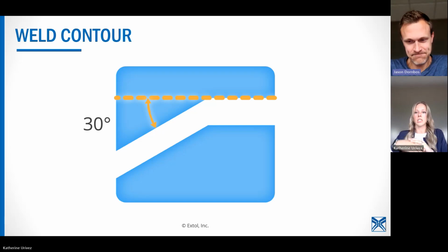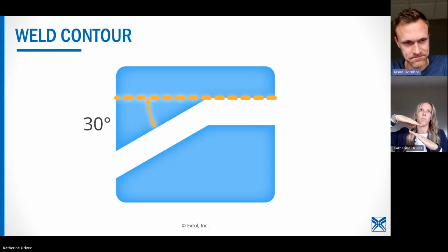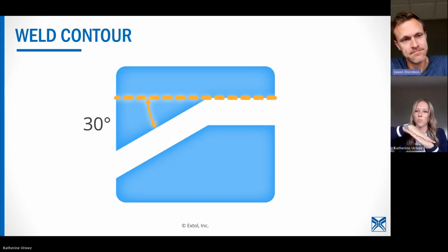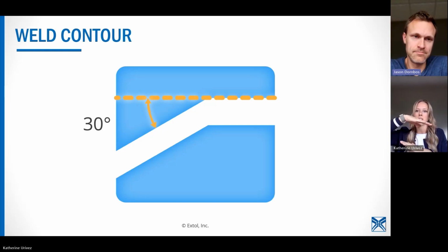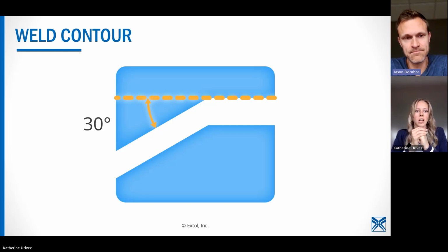The reason for this is when the parts come to seal together, that angle starts to act as kind of a slide. And so you're smudging that molten material past itself, not necessarily getting a good force into that angle. So that's kind of the reason why 30 degrees is our recommended angle maximum. We have done a little bit more than that. So if you have an application where you just can't get to 30 degrees, let's test it. Let's see if we can hit your specs.